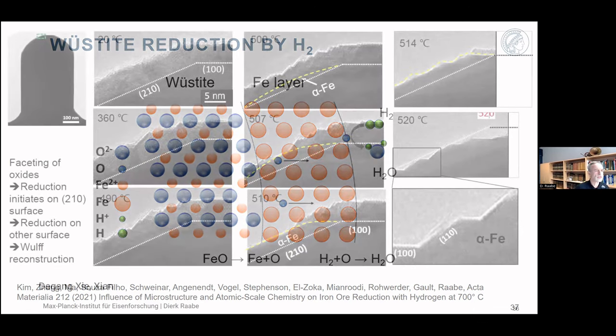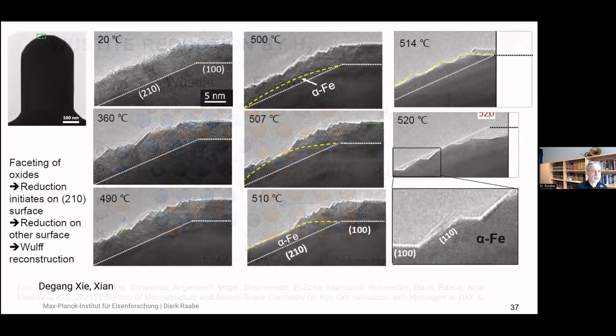When you go into detail, that is another high resolution experiment in a hydrogen flooded electron microscope, done here by our Humboldt fellow Degang Xie. Then you see that, for instance, when we look at the 500 degree centigrade image, you have a strong dependence on the crystallographic faceting. You see here that the alpha iron, for instance, with a 210 facet is already readily formed and reduced, while on this other facet, the 100 facet, you still have the complete oxide layer on top. That was purposely oxidized iron nanocrystals to make them visible in the electron microscope.